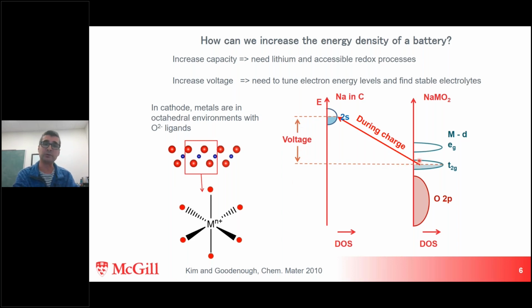So if we want to increase our voltage, we have to move these bands down. If we want to increase the capacity, the amount of lithium, or in this case sodium, and the amount of redox that's accessible, well, we can basically empty out this d band, and then we need more redox. And in a lot of these materials, the oxygen is too low. It's at too high a voltage. So the other thing we can try to do is move these oxygen bands up so that we can access them. That's another way to get higher energy density. And I'll come back to this in my group's data in several slides. But this is conceptually what's going on in the battery.